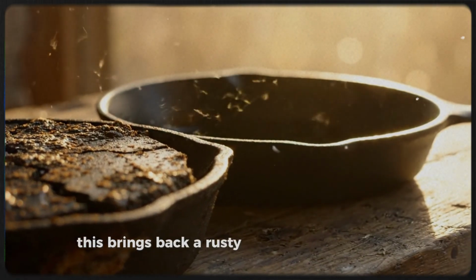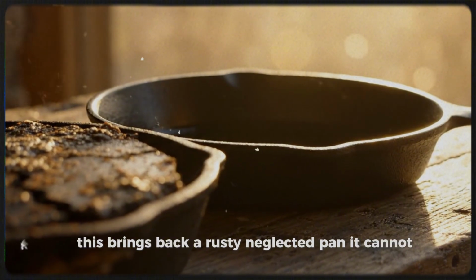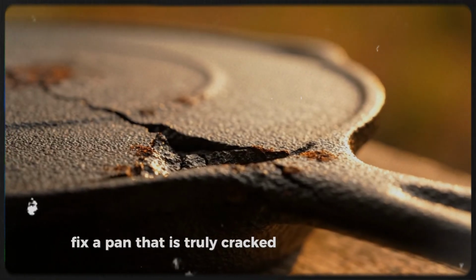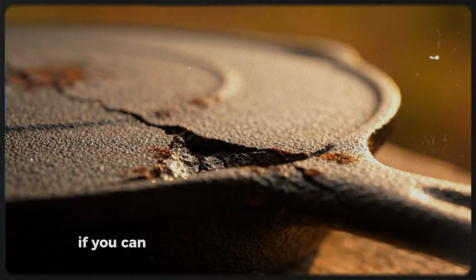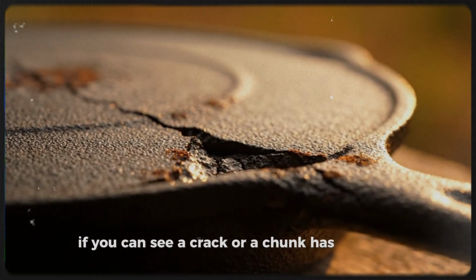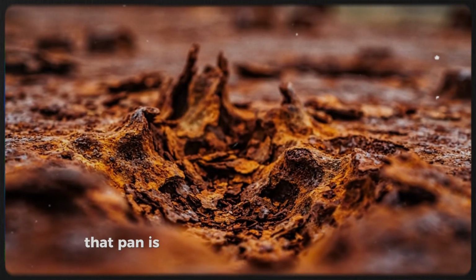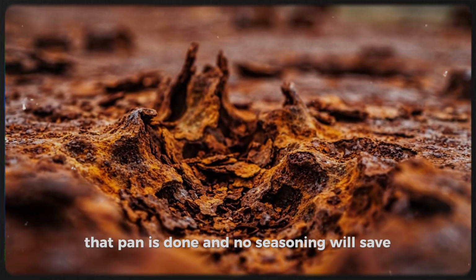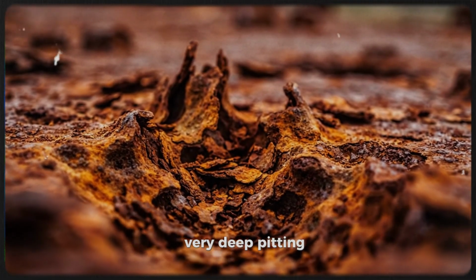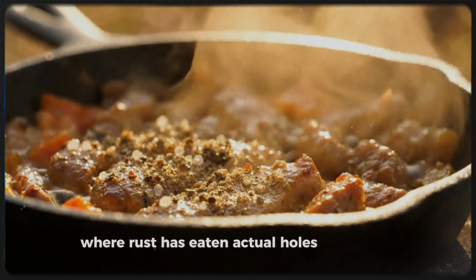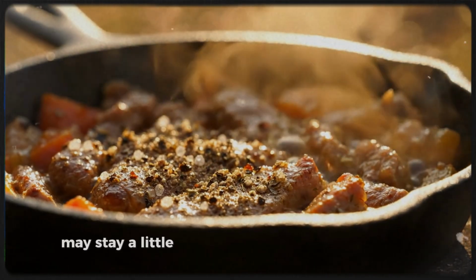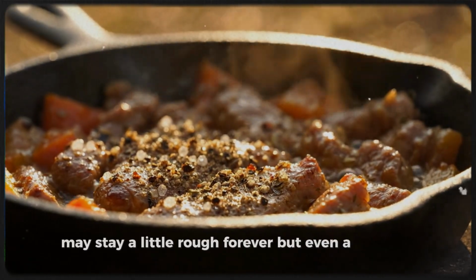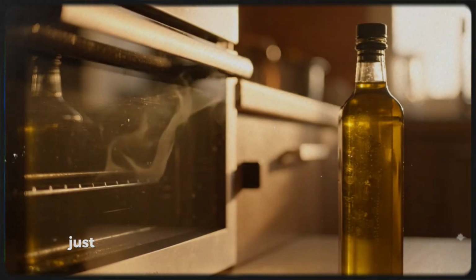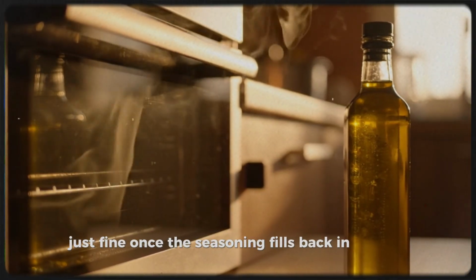Now let me be completely honest with you about what this method can and cannot actually do. This brings back a rusty, neglected pan. It cannot fix a pan that is truly cracked all the way through. If you can see a crack or a chunk has broken off, that pan is done, and no seasoning will save it. Very deep pitting, where rust has eaten actual holes into the iron, may stay a little rough forever. But even a pitted pan will usually cook just fine once the seasoning fills back in over time.